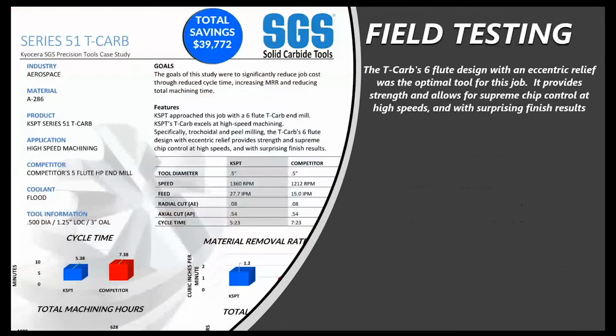This case study is based on a cost savings we offered a customer cutting A286 stainless in aerospace. They were using a competitor 5-flute end mill with a trochoidal tool path. Both end mills were half-inch diameter, programmed to take 540 thousandths axial depth of cut with a radial engagement of about 7%.